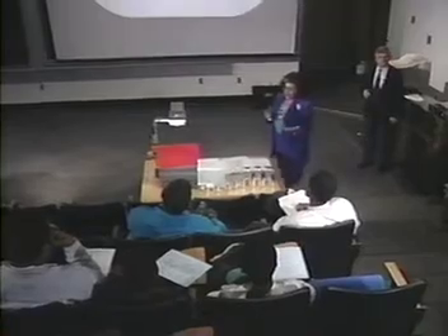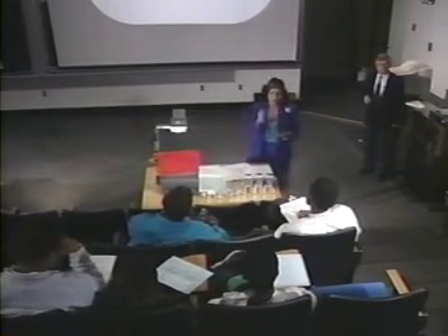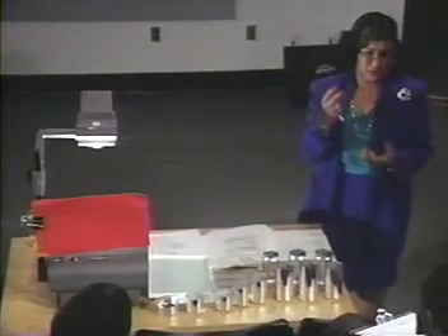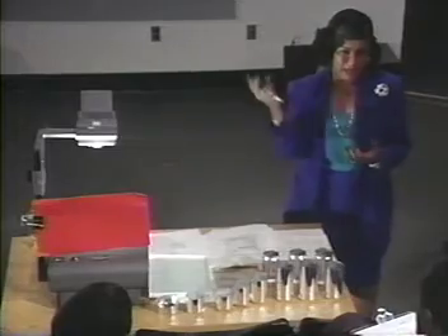Fracture toughness is the ability to stop a crack from becoming a catastrophic failure. One of the things that you don't want to happen is for a crack to reach a critical size in a metal part, because then it runs at the speed of sound and you can't stop it. So you want a material that's going to dent, absorb some of that impact energy in deforming the material, and not shatter. A357, because of the heat treatments and the composition and the chemical treatments, is grain refined. The structure is also internally modified with strontium or antimony, so that there's a defined morphology to the second phase particles, the excess silicon that's left.